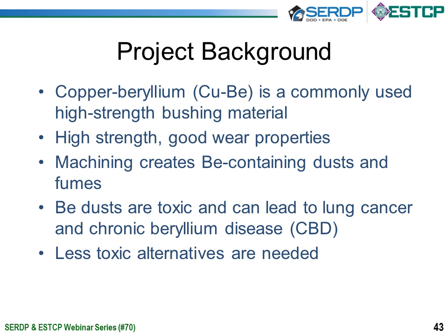So the project background, copper beryllium. It's the hardest and strongest of most of the copper alloys, 2% beryllium typically. It's a preferred high-strength bushing material, used in a lot of aerospace applications. It's got high strength, excellent wear properties in terms of low coefficient of friction, high galling resistance. Has other advantageous properties too. It's a non-sparking material. It's non-magnetic. Has good high temperature performance, good corrosion resistance, amongst other properties.